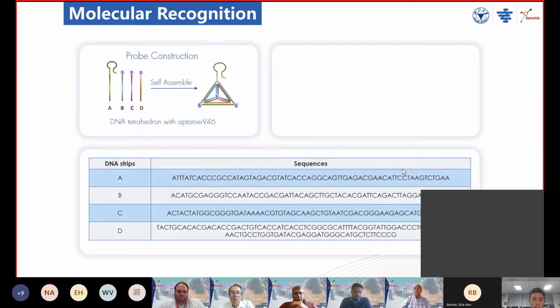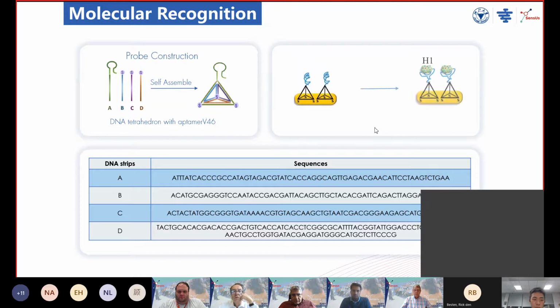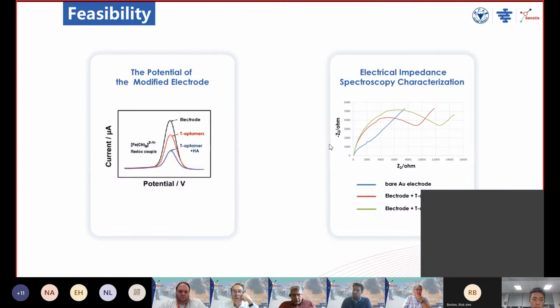And we also developed another approach, a DNA tetrahedron with aptamer as a probe. This is the 4 strands and its sequences. As you can see here, it is possible for them to self-assemble. By this means, we can achieve good orientation on the electrode surface and fewer modification steps, because the location of the sulfur on the 3D structure of the tetrahedron is fixed, and the cross-linking step is not required. To verify the feasibility of such a method, we measured the voltage potential and electrochemical impedance spectroscopy. As a result, each step of the modification was proved to be successful.